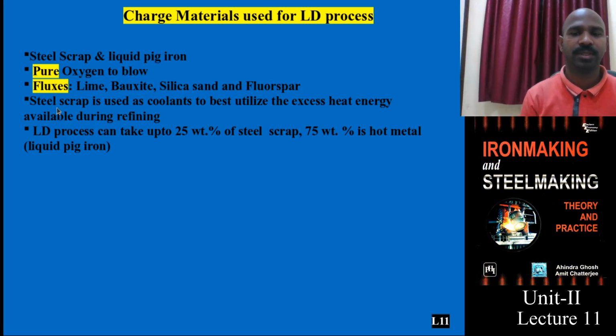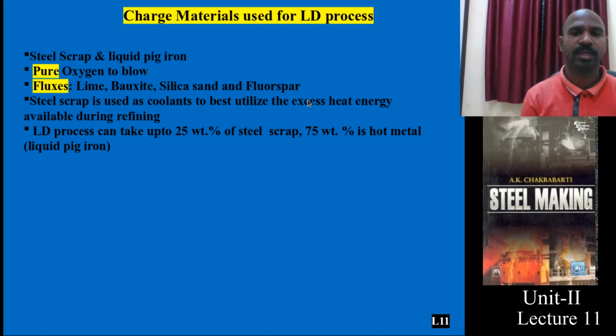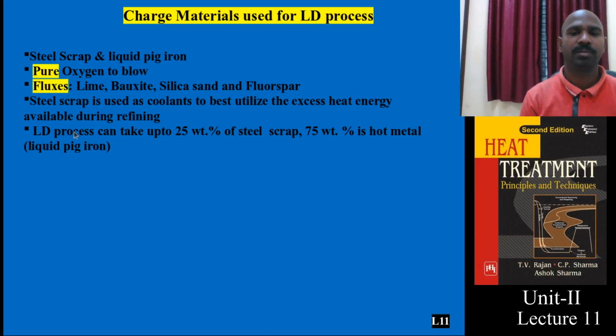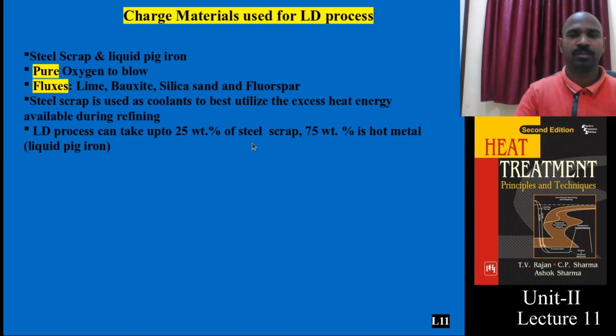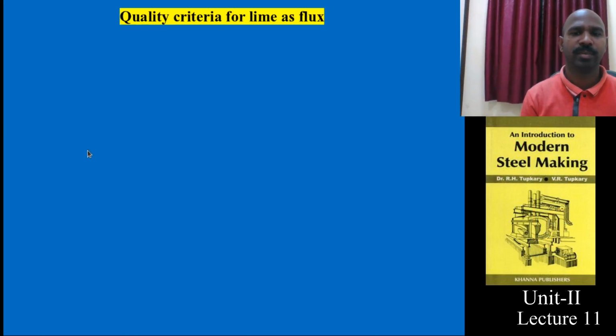One needs to notice that the steel scrap acts as a coolant, balancing the heat energy so that it does not go too high in the chemical reactions. The LD process can accommodate steel scrap up to a maximum of 25%, and the remaining is hot metal, which is nothing but liquid pig iron. Please make a note.